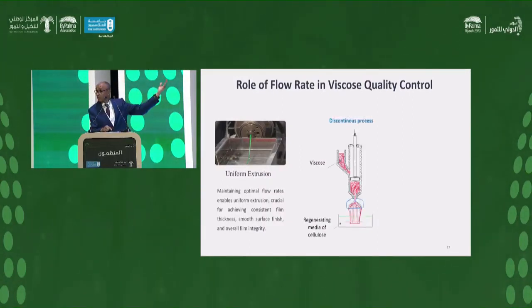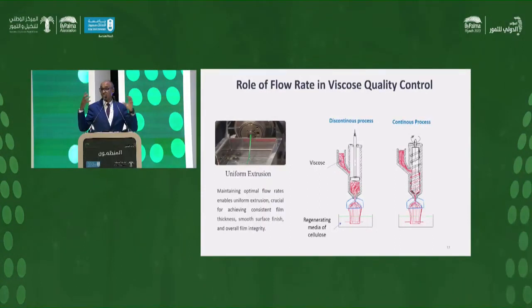But in our case, it is difficult to use this process, and we can use a vertical flow of the materials. This is a schematic of how the process can be designed and can work. In this discontinuous process, we have the quantity of the materials and it is pushed through a die. This is a flat die to have a film, and we have a regenerating media of cellulose. And also we can use a system as extruder, and we have the screw and the material flows through the die, and we can have a continuous flow of the material and a continuous process.